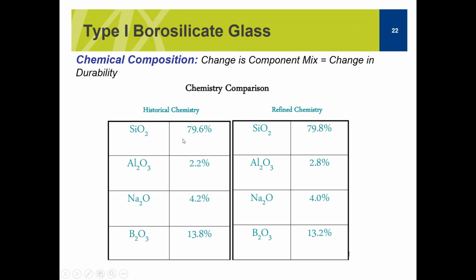So silicon oxide, they increased it from 79.6% to 79.8%. So this is very small, but you will see how dramatic the effect is. They also increased the aluminum oxide. What they decreased here is sodium oxide and boric oxide. These are the two they changed, and really the sodium is the enemy in glass in terms of extractables and leachables. And again, this is a network modifier, so they decreased it from 4.2 to 4.0.